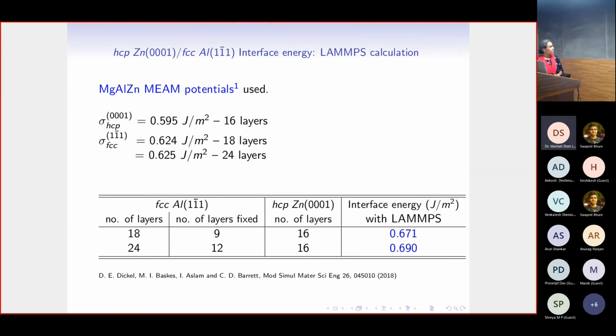Okay. So with this now, for the two different slab thicknesses, we get the interface energies, and we see that they are differing very marginally. Which means that this 18 and 24 layers is a reasonable thickness that we can work with. So we know how to do this now for aluminum zinc.